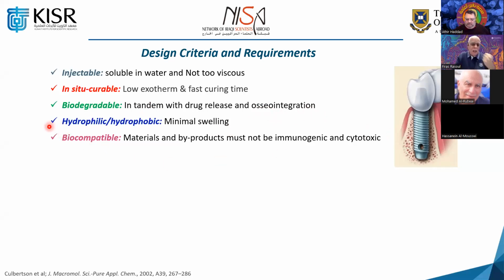The other very, very important criterion is the hydrophobicity ratio. You don't want your material to be a hydrogel that is extremely hydrophilic, because it means it's going to absorb a lot of water and it's going to swell. And if it swells, then it will not be comfortable in any patient's mouth. So we really need to control the swellability and the water absorption of this hydrogel. So you need to have a balance of the hydrophilic characteristics of this material.